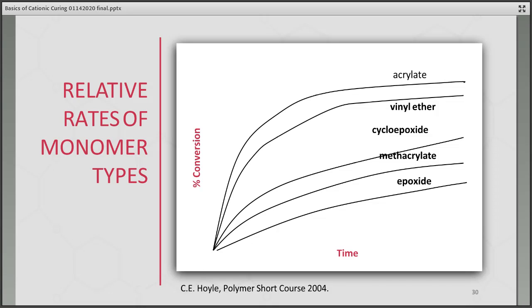Here's comparing the rates. I mentioned how fast vinyl ethers are in the previous slide. So let's compare them. Usually the good benchmark is acrylates. They're very fast reacting in free radical systems. Vinyl ethers actually react very close to the speed of acrylates. So that's where you get your boost in reaction speed. Next down is cycloaliphatic epoxides, followed by methacrylates, and regular aliphatic epoxides tend to be the slowest in the system.